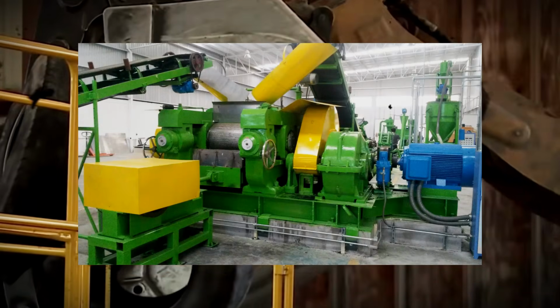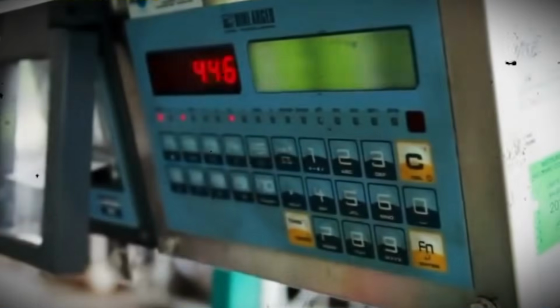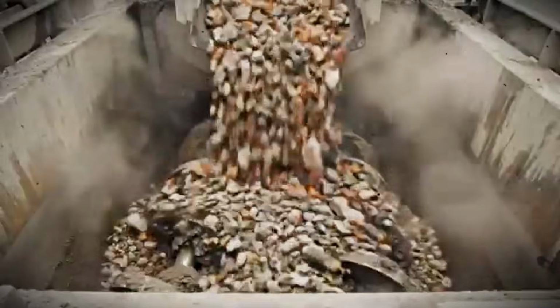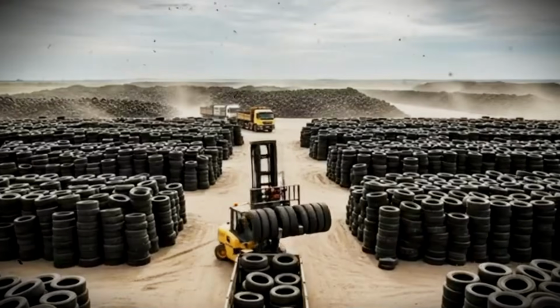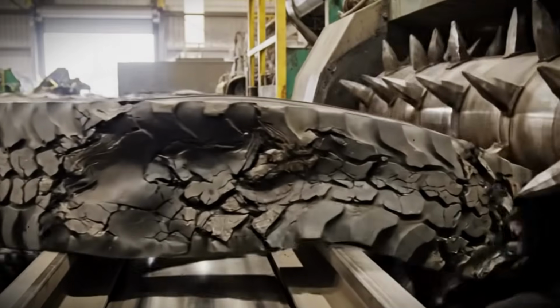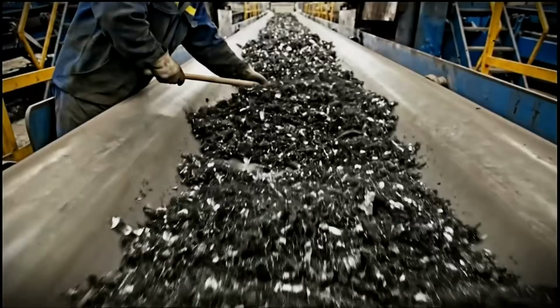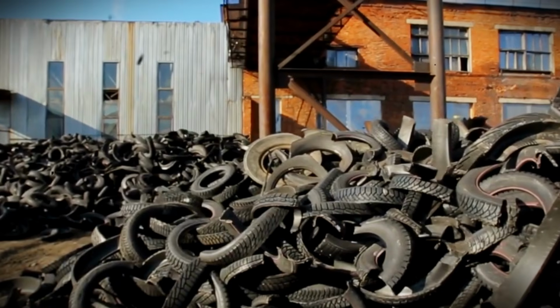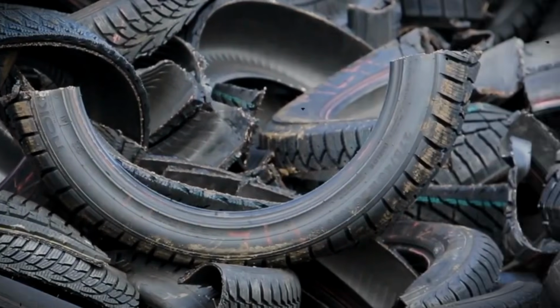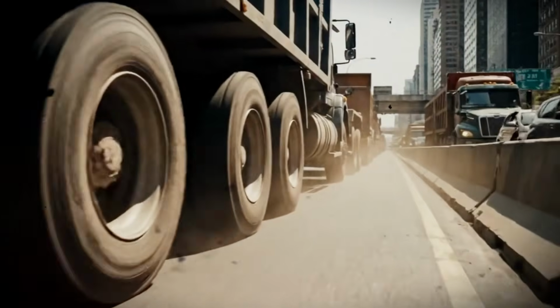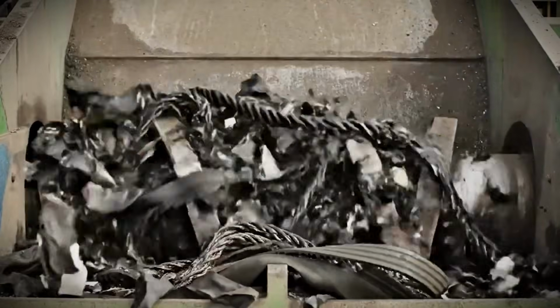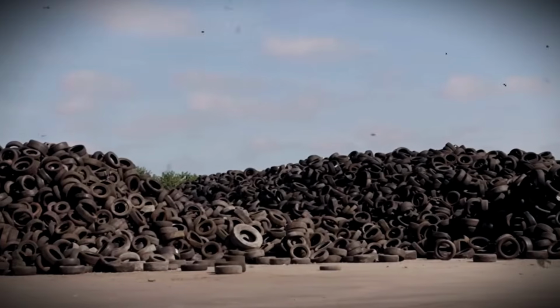Enter the cracker mill. The cracker mill is the heart of the operation. Inside, heavy steel rollers spinning at different speeds literally crack the rubber particles apart at the molecular level. Temperature control is critical here. The friction generates heat, and if it gets above 200 degrees Fahrenheit, the rubber starts degrading and loses the properties that make it valuable for asphalt. The rubber passes through the cracker mill multiple times, getting finer with each pass. Pneumatic screening systems separate particles by size using vibrating mesh screens, with openings measured in fractions of an inch. The material that passes through is called crumb rubber.